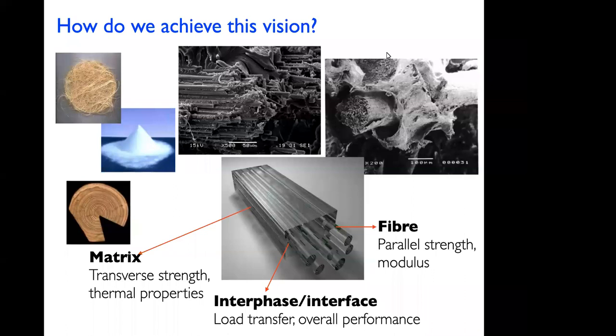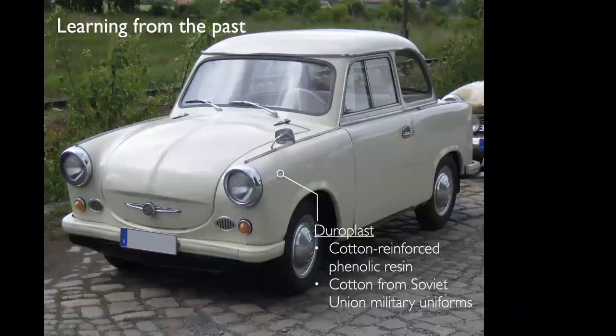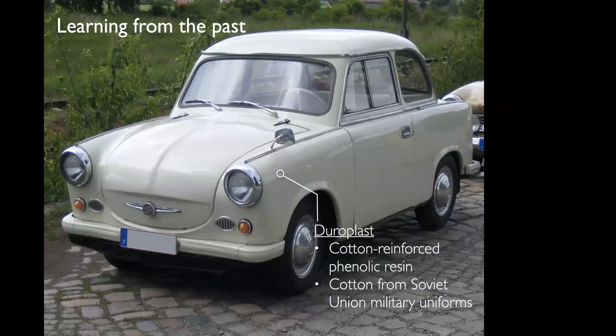The picture in the top right corner shows an image of a natural fiber reinforcing a thermoplastic polymer matrix — the hole between the fiber and the matrix is the interface; in this case there's actually no interface, so the composite performance is rather poor. The center top picture shows an SEM image of a carbon fiber reinforced polymer composite. Creating fiber reinforced polymers from waste materials for a circular bio-economy is actually not a new concept — this car was built in East Germany back in 1957.